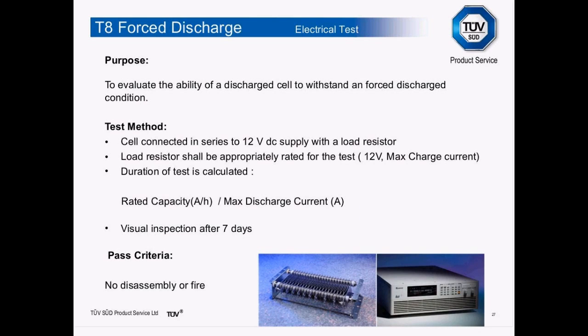The T8 test is the forced discharge test, evaluating a discharged cell's ability to withstand a forced discharge condition. The cell is connected to a 12 V power supply with an appropriate load resistor rated for 12 V and the maximum charge current as specified by the cell manufacturer. The test duration is calculated by dividing the rated capacity in amp-hours by the maximum discharge current in amps. After the test it is left for seven days, then a visual inspection checks that no disassembly or fire has occurred.